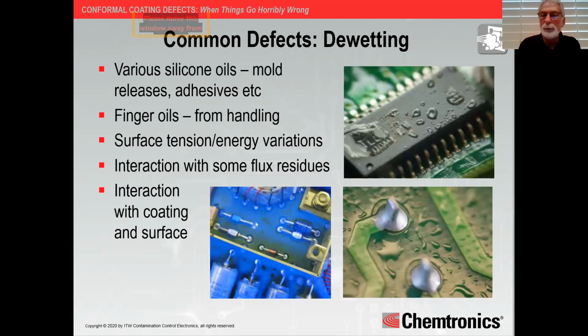Now we're getting into, and we have labeled these as common defects. Consider these as common conditions. They may or may not be a defect depending on how your criteria are set up. De-wetting is essentially where the coating pulls away from that surface because of differences between the surface energy. It could be a contaminant on there. As mentioned here, it could be little spots of silicone oils from mold releases, adhesive residues. It could be oils from your hands and your fingers from handling the board if you're not properly taking those precautions. Again, surface tension and surface energy variations. That coating is not allowed to properly wet and then bond to that surface.